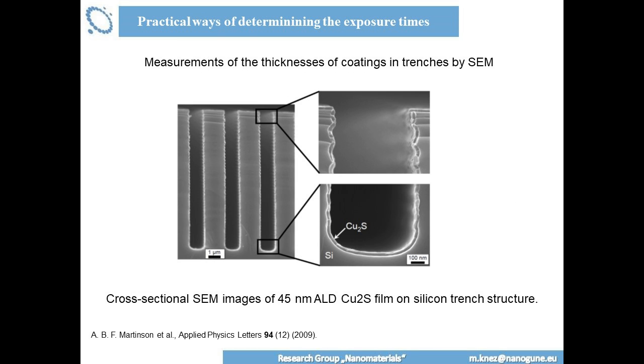So, if you want to go practical, you have proper parameters you want to measure whether they are okay. Then how do you do that? Just a few examples on how to measure the thicknesses of coatings. Of course, you can do cross sections and you do SEM images. You take a top and the bottom of a pore. In this case, it's just an example from literature.